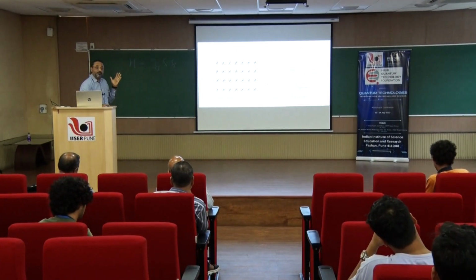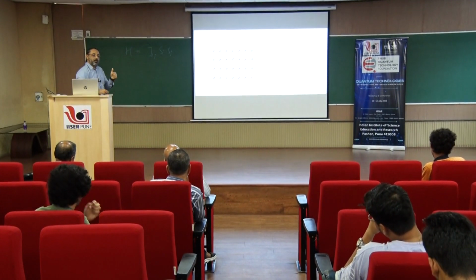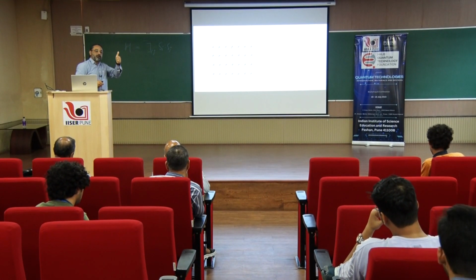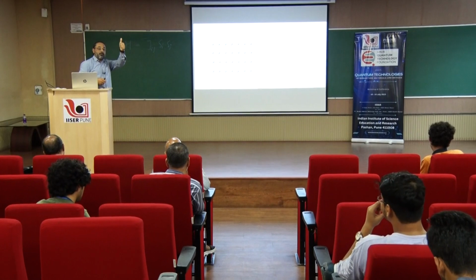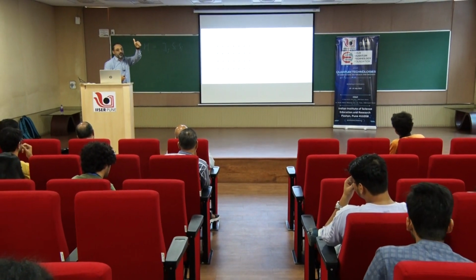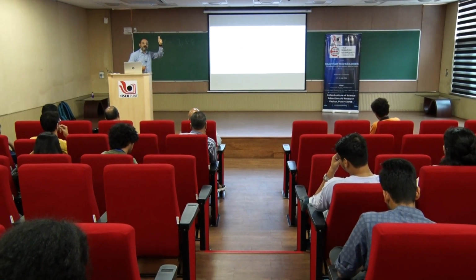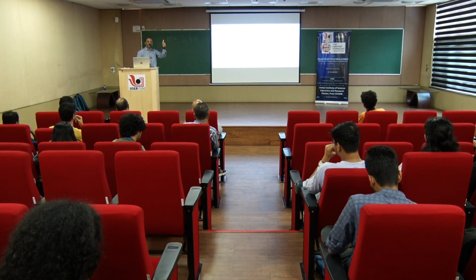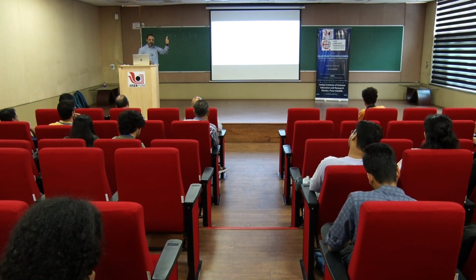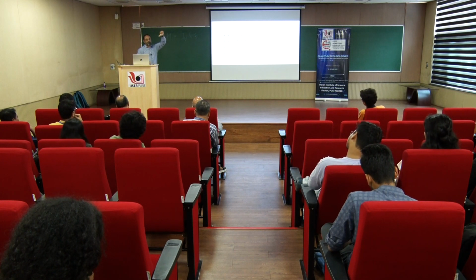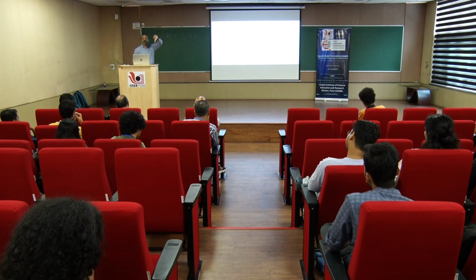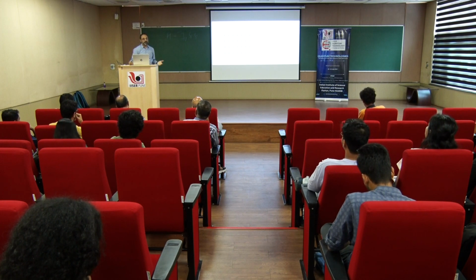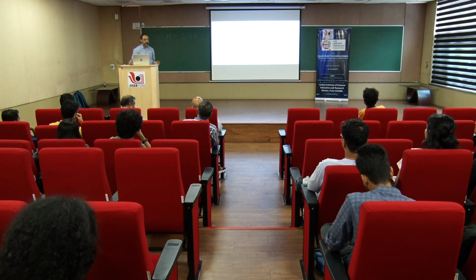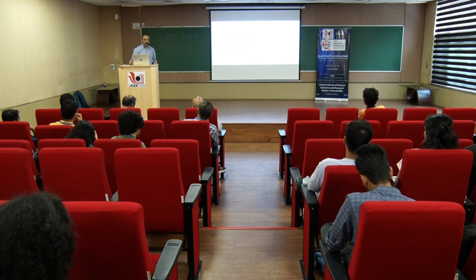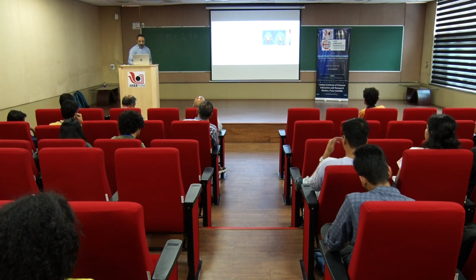If your spin is 5/2, let's say, then what would your transverse operators do? The transverse operator would take 5/2 to 3/2 or to 1/2. But in the case of spin 1/2, once the transverse operator works on the spin 1/2, it goes from +1/2 to -1/2. So it's as disruptive as this, and that is what it means by quantum fluctuations or very strong quantum effects in a spin 1/2 chain, and not in the higher spin chains.